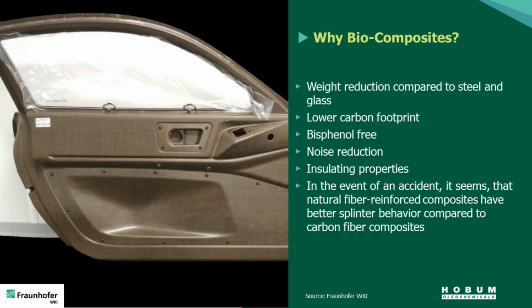Well, first of all, we have a weight reduction compared to steel and glass. In total, we found out in an LCA study during the project that we also have a lower carbon footprint. We can make this door bisphenol free, which is also a topic of the future if we talk about epoxy. It turns out that natural fiber composites can help noise reduction. They have better insulating properties, and also it seems that in the event of an accident, the splinter behavior of natural fibers is better than compared to, for instance, carbon fiber.